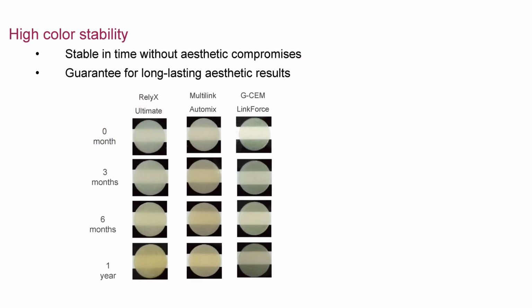Another important aspect of G-CEM LinkForce is its high color stability. That means it is stable with time without causing any aesthetic compromises, and it guarantees long-lasting aesthetic results. Now, what does this mean? When a veneer is cemented or luted, over a period of time, within a year or 2 years, you'll see that the veneer starts losing its sheen. It starts becoming dull. It's not that the veneer has become dull, it's basically the aesthetic resin cement undergoing degradation. And this color degradation is because of the tertiary amines which are present in these aesthetic resins.